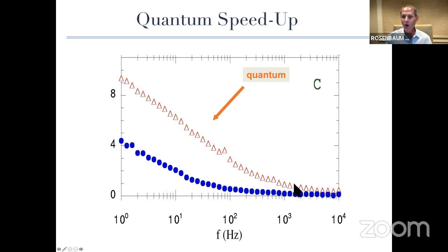And this is the so-called F0 that I'm going to come back to. These are the most weakly pinned domain walls when they start moving, okay? Because of course I have a bunch of domains and I want to flip them to get the alignment and the net magnetization and the divergence of the susceptibility as I'm entering into the ferromagnetic state, okay?